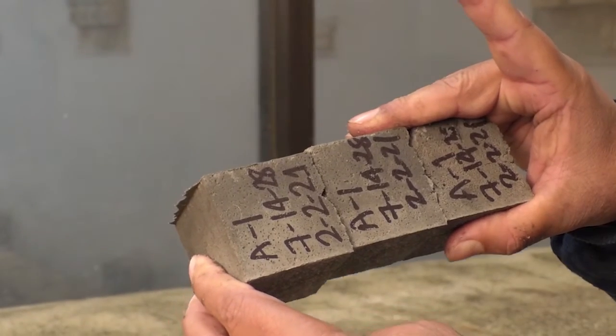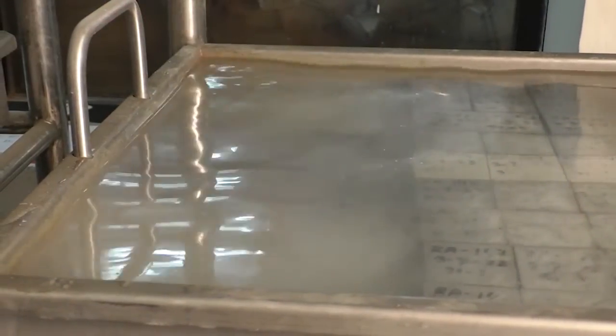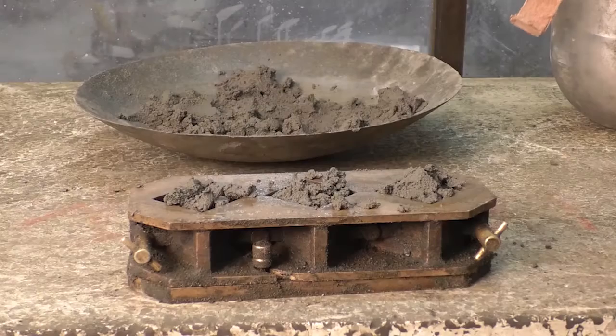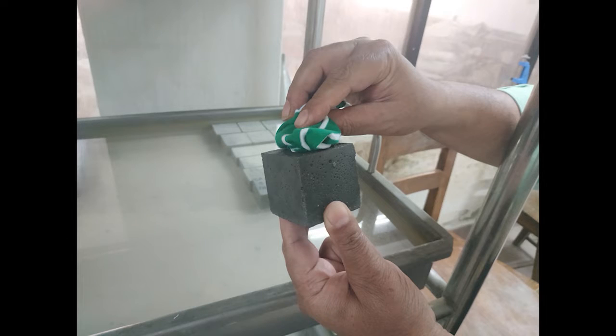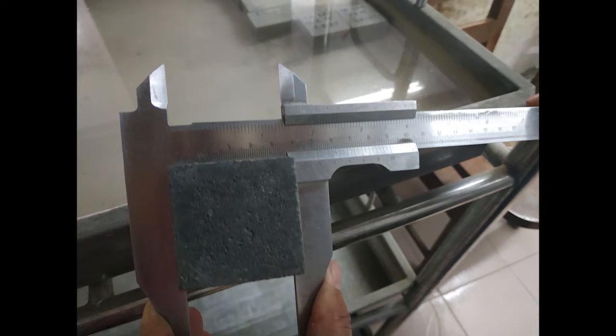We have to immerse the specimens after demolding in saturated lime water in storage tanks constructed of non-corroding materials. This process is called curing of the specimens. After removing a specimen from water for testing, we have to wipe each specimen to a surface dry condition and remove any loose sand grains from the cube face. Then we have to measure the critical cross section dimensions to the nearest 0.01 inches prior to testing.